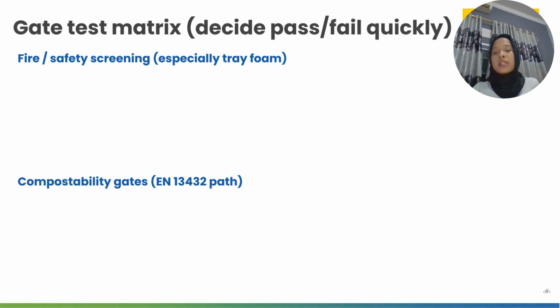And the last one is compostability gates, where the first one is disintegration, and the test is industrial compost conditions, and the pass criteria is no visible residue beyond the allowed limit. The second one is mineralization, carbon evolution versus a reference test, and it requires a percentage within the time frame. And the last one is ecotoxicity, which is compost plant growth plus heavy metals, and no adverse effect.